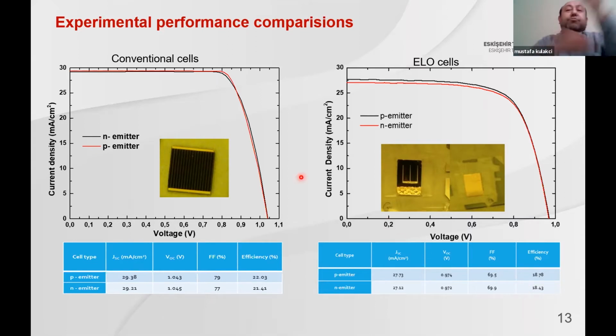Of course, in design and simulation, it was opposite, which means n-emitter was much higher compared to p-emitter, but after production, we see the opposite. Most probably those are due to production changes in our laboratory. When you look at conventional cells, actually there is no shunt loss. The losses are all related to series resistance, but in ELO cells, there is a huge amount of shunt loss. Also, in the same way, there is a huge amount of series resistance loss. When you look at fill factor, in the realistic case, it should be around 85 or more than 85, but due to series resistance, it decreased to much lower than 80%. Also, the metal shadow is a bit higher. It should be decreased to almost half of it.